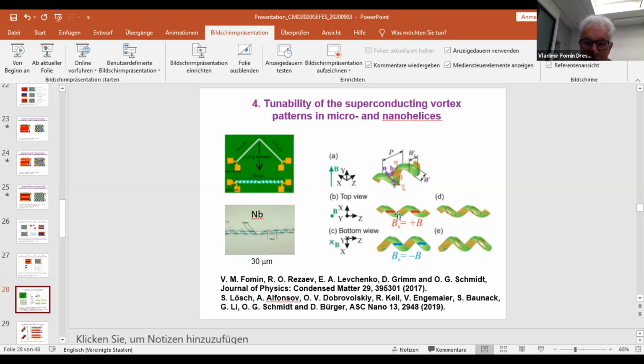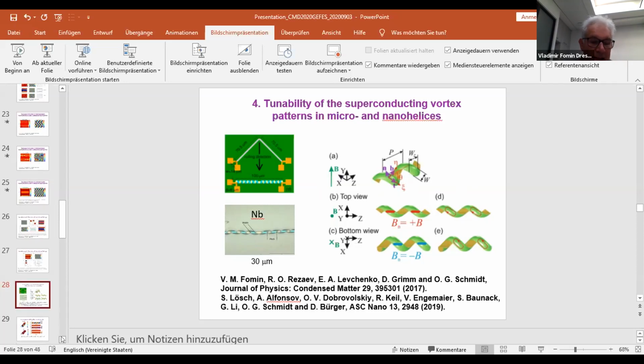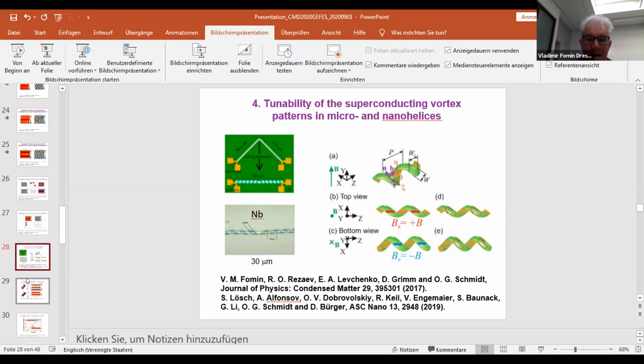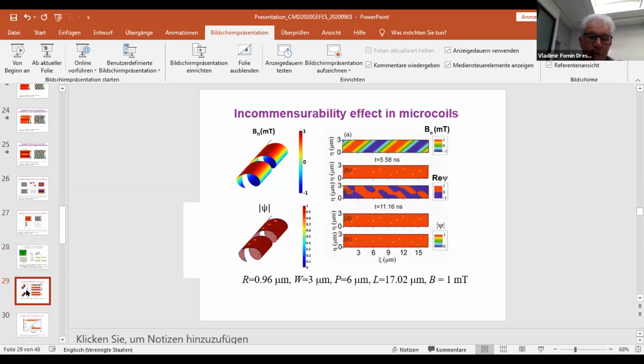And in these structures, as you see here, in the case of magnetic field orthogonal to the axis of a nanohelix, you see screening currents flowing in multiple windings of a helix in the upper and lower parts of them, so that we can expect even more complicated pattern of vortices. And this is indeed confirmed by calculations of distributions of vortices, first in quasi-stationary state.